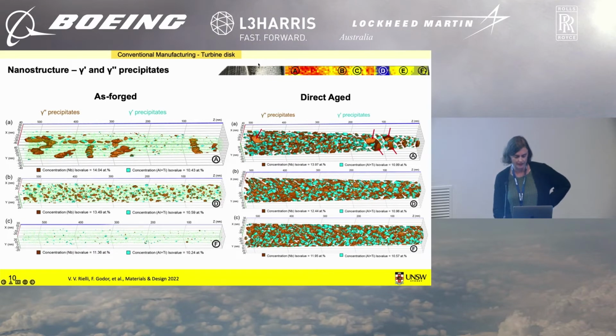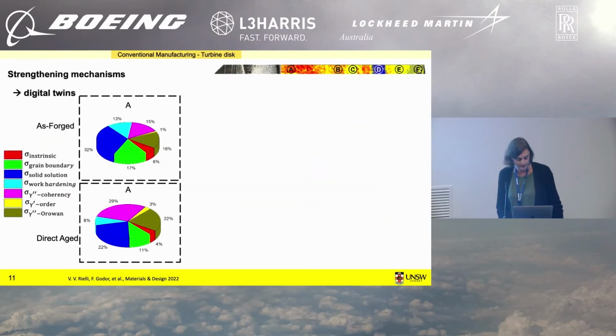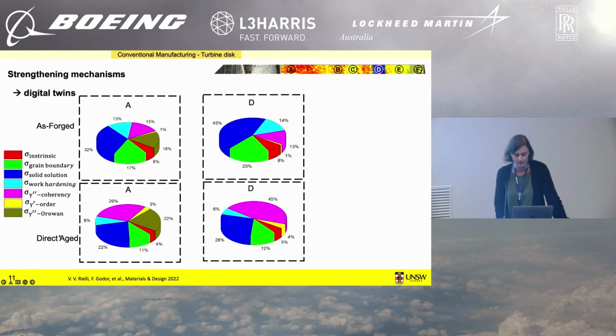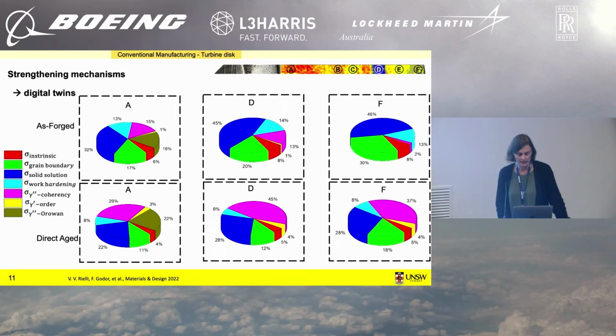So after forging, there's only a little bit happening. The good news is the direct aging process is really robust, and if we subject these disks to a final thermal treatment, we achieve what we want to have, a very kind of dense and interconnected nanoscale decoration with precipitates. So that's all very nice, but why is this useful? So my industry partners can create digital twins where we can very accurately predict all the various strengthening contributions. So don't worry about the details here, but there's many, and that's related to the microstructure, and we can do this for all these different positions, and then create turbine disks with better properties.